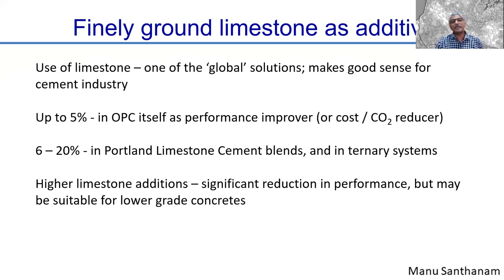However, there are so many applications in which concrete is used where lower grade concrete can be utilized. For instance, in non-structural applications like curbs, dividers, blocks and things like that. In such places, there is no need to worry about using very plain cement or very large amounts of ordinary Portland cement. You can go for very large levels of replacement, even with limestone that is not suitable for cement manufacture. That means the lower grade limestone that is available in the mines associated with the cement plants. You have a lot of limestone that is not suitable for cement manufacture. There's tons of it available. And this limestone can be extracted and utilized for making lower grade concretes that are good for non-structural applications.